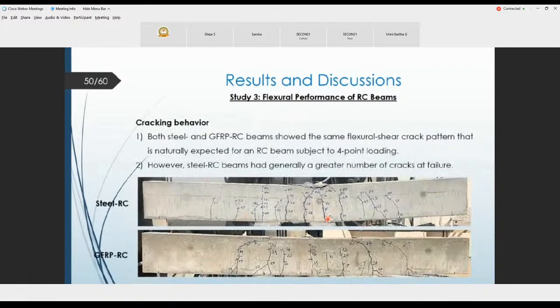For the cracking behavior, this shows a comparison between these two beams at failure, one steel reinforced and the other GFRP reinforced. Both steel and GFRP reinforced beams showed the same flexural shear crack pattern naturally expected for an RC beam subjected to 4-point loading. However, steel reinforced concrete beams had generally a greater number of cracks at failure.